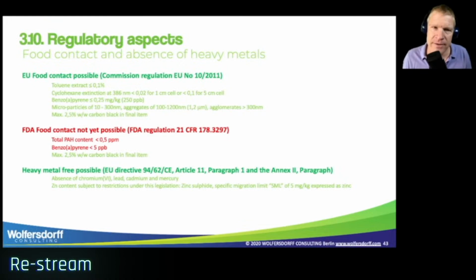The third regulatory aspect is very often master batches require a declaration, or the packaging customers of the master batch require a declaration that the master batch is heavy metal free. And this is the European Directive 94/62/EC, Article 11, Paragraph 1, and the relevant Annex 2. And this is about the absence of chromium-6, lead, cadmium, and mercury. So thumbs up. You might have worried that in recovered carbon black, we have zinc, which is a heavy metal. This is not considered in this directive, so thumbs up.